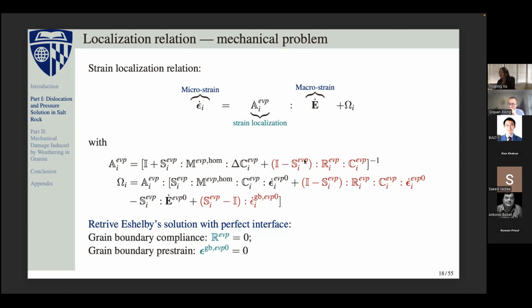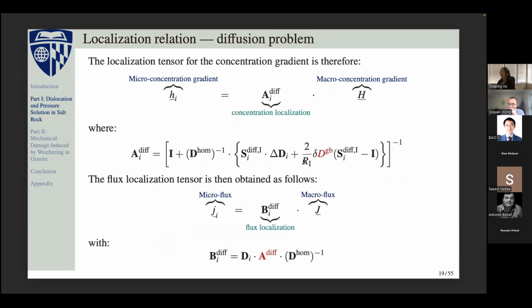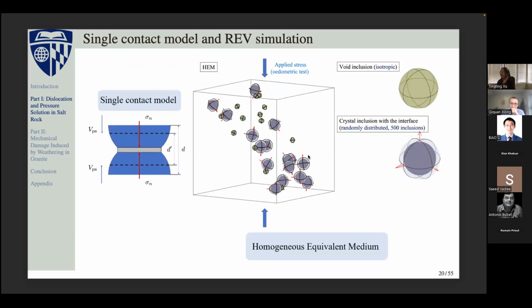So this is a linear relation, and we also provide this linear relation for the diffusion problem. That means in addition to this mechanical problem, we have a very similar phenomenon, at least from the formulation. We have a linear relation that can bridge the micro concentration gradient to the macro concentration gradient, and from the bottom equations, you can see how it bridges the microflux to the macroflux. So with all these equations, we have a local behavior, and we have the linkage between the local behavior and the global behavior. We can simulate it at a laboratory scale.